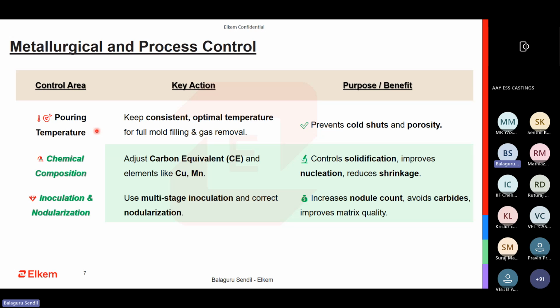Make sure that it doesn't collapse. Apart from that, you should keep it at a very optimal temperature. We will touch upon that. The second thing is the chemical composition, which is with respect to carbon equivalent. The most important point for shrinkage reduction is having the correct carbon value and the silicon value. This more or less, for the particular casting section thickness or solidification rate, determines how much of a risering design is required. So the carbon equivalent selection is very, very important. There are a few guidelines which I would like to show in the upcoming slides.